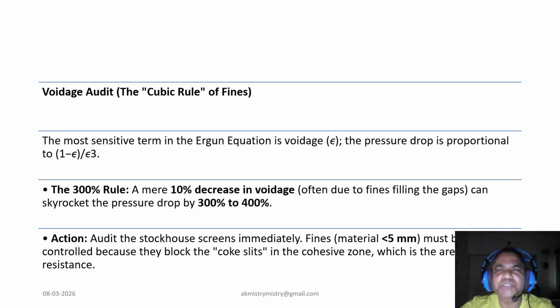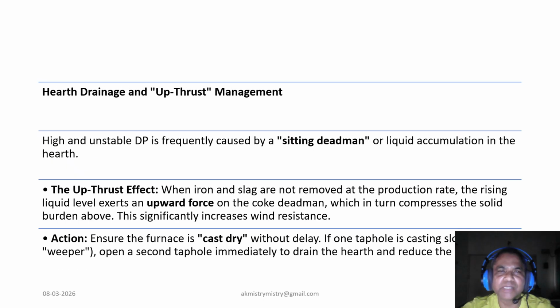Sometimes the pressure problem is not at the top, it is at the bottom. If the iron and slag are not removed fast enough, they create an upthrust against the coke deadman. This upward force compresses the solid burden above it, making it much harder for wind to pass through. Then what is the fix? Ensure the furnace is cast dry without any delay. If one taphole is slow, open a second one immediately to drain the hearth. So we need to ensure that there is no constraint or delay in hearth evacuation.